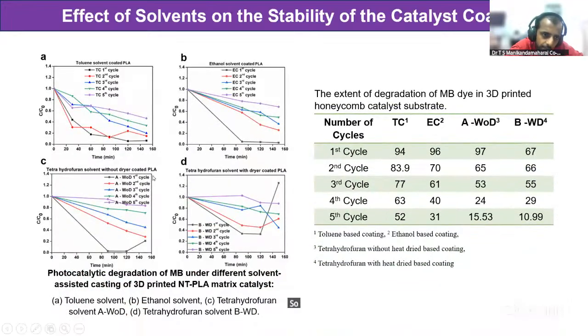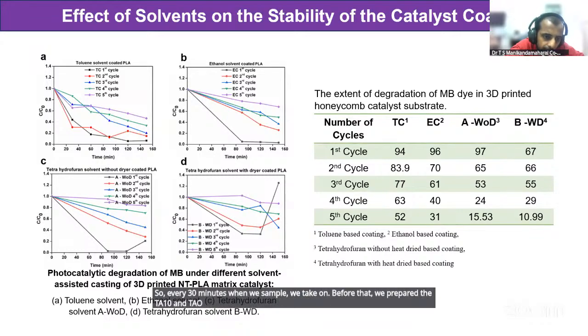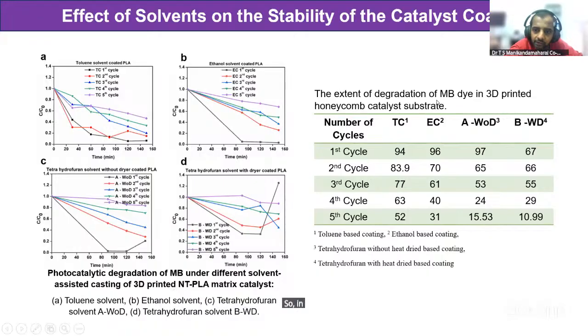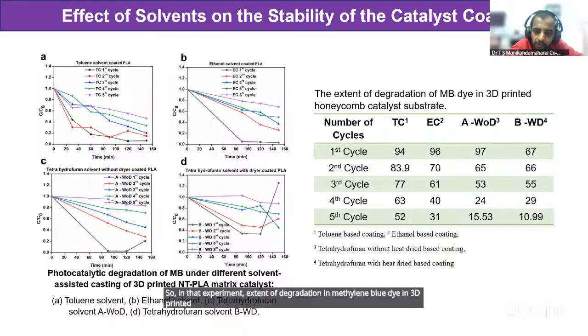So every 30 minutes we take a sample. Before that, we prepared the TiO2 and N-TiO2 coated onto the substrate. We are taking a suitable additive solvent. Here we are taking types of solvent: toluene, ethanol, and tetrahydrofuran. With these different types of solvent, the one giving the best result is optimized and attained. So in that experiment, we looked at the extent of degradation of methylene blue dye in the 3D printed honeycomb catalyst.